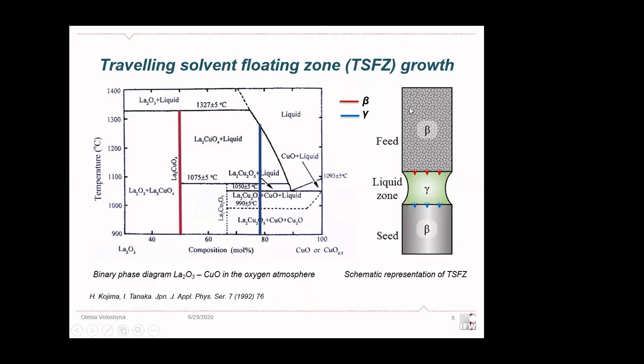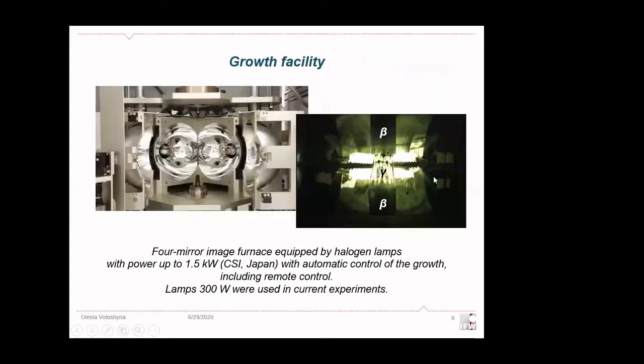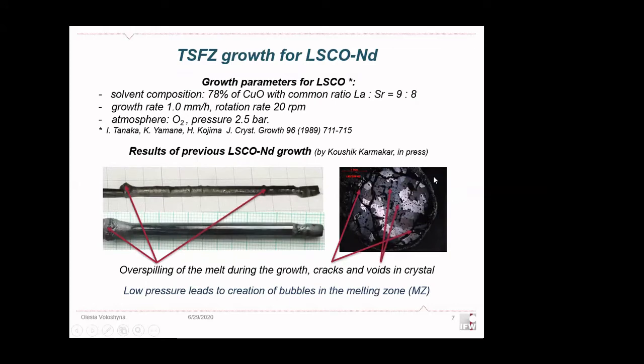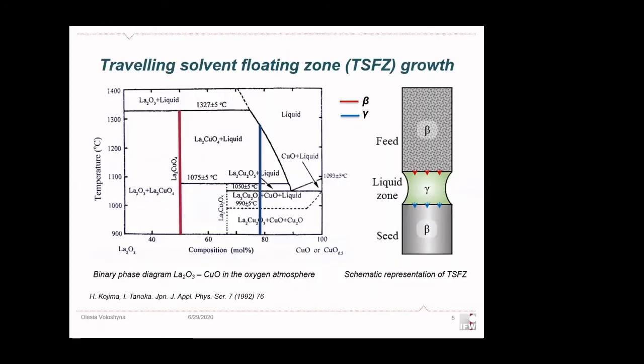that can be schematically represented like this. We use the feed with composition beta that equals our goal compound. You can see it on the phase diagram. We attach some kind of solvent. The solvent is usually chosen from a composition relevant to the liquidus line below the peritectic point, the decomposition of our compound, and above the eutectic point. And this solvent forms the melting zone.